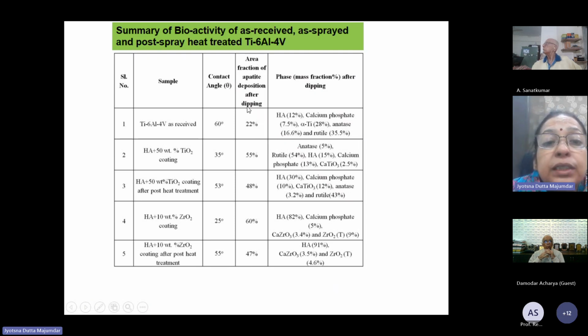So what we found is that the area fraction of deposition after dipping is 22% for Ti6Al4V. However, due to hydroxyapatite coating, it is 55%, and after heat treatment, you find that there is a little bit of reduction in the area fraction of the apatite formation.